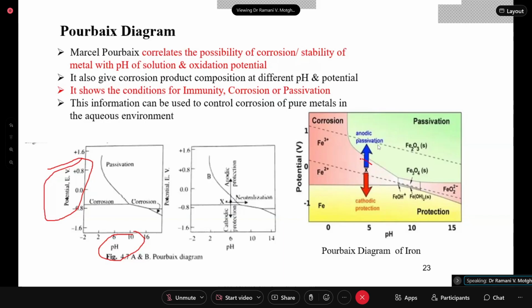Now what is it saying? If your iron metal is held at this potential value, and you render it cathodic, that is, you connect the negative terminal of impressed current or attach it to zinc or magnesium, it will start behaving as cathode. So this becomes cathodic protection. Here it is in the zone of corrosion. But once you apply a positive potential and make it anodic, it gets passivated because of the formation of an oxide film which protects the underneath layer. By increasing the potential to some extent, you are passivating it. So anodic passivation or anodic protection is termed this green zone.